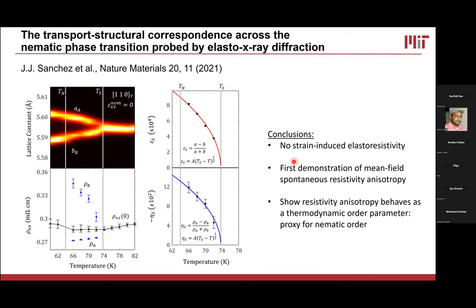And we hadn't been able to show this in the past because we didn't have a clear indicator of how much we've detwinned the sample. Because if you apply any extra strain at all, you get additional resistivity anisotropy, and that can blur this picture. But by doing this combination of techniques, I was able to show that the resistivity anisotropy really does follow the nematic order parameter in the nematic phase.